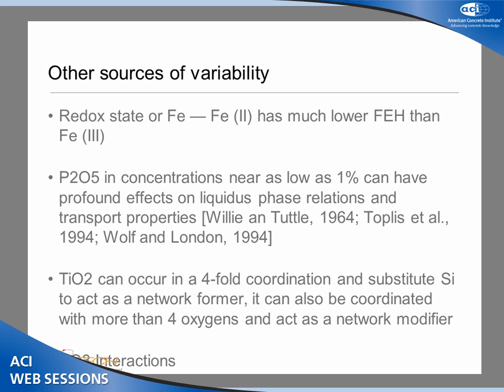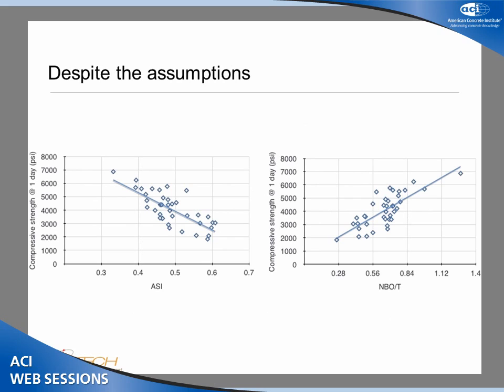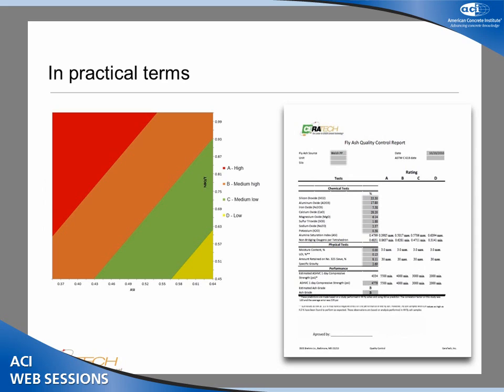And here on the bottom, you can almost see it. SO3 interactions. We didn't really consider SO3 interactions. That's also something that could have an influence there. However, despite all the assumptions, it seems to work very well. So in practical terms, we have this surface graph where you can locate the reactivity of your ash, A, B, C, or D. A being the most reactive ash, to D being the lowest reactive ash. So you can locate that here. The alumina saturation index is on the x-axis, and the non-bridging oxygen per tetrahedron is on your y-axis.